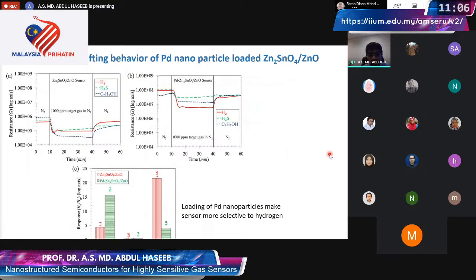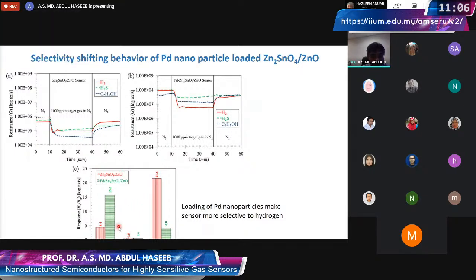And what we see here is quite interesting. So originally, if you remember, the mixed oxide was more sensitive to ethanol and less sensitive to hydrogen. So its response is 4.4 against 21.6. But once we put palladium nanoparticles in the system, then things get reversed. It becomes more sensitive to hydrogen and less sensitive to ethanol.